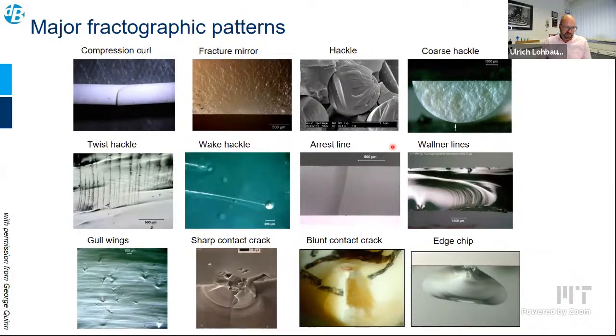There are examples, most of them in glass, but these are typical examples which we can find on a brittle surface, like ceramic or even filled polymers. So the easiest is always the compression curl, which is on the opposite end of the fracture mirror. And this is actually an inclination of the fracture plane when it comes under compressive loading. So the compression curl is in most cases found, and we need to seek the fracture origin in the opposite direction. The fracture mirror is very typical.